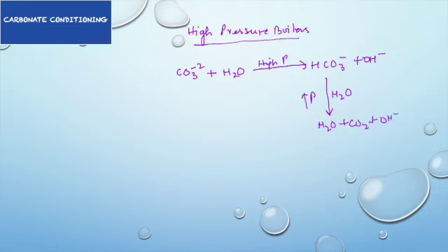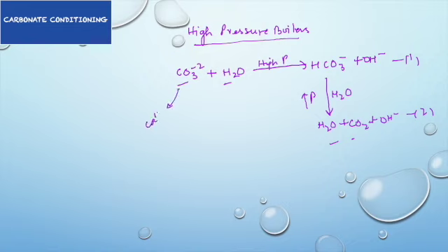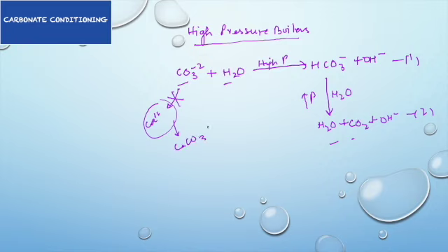Because of these two reactions, the concentration of carbonate ions gets reduced — the carbonate ions are consumed by water and converted finally into CO₂ and water. No more carbonate ions are available to capture calcium ions, so this route is blocked. It becomes impossible for the solution to become saturated with respect to calcium or magnesium carbonate, making loose sludge formation impossible.